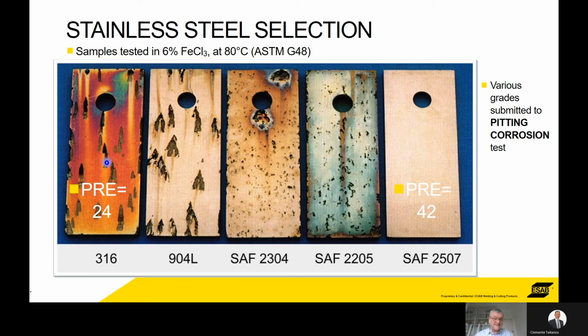And the thing with pitting is that, like an iceberg, underneath is where all the damage is. There's more damage below the surface beneath these pits. As you're going up the scale, we've got a lean duplex, so a standard duplex, 2205 standard duplex.